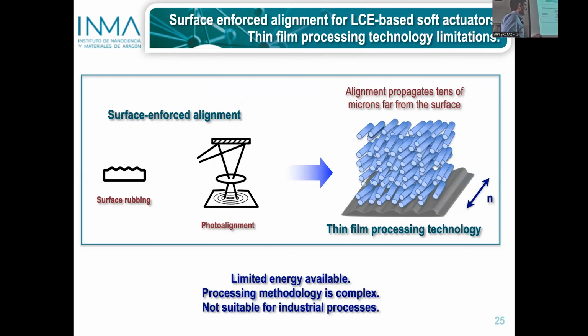Okay, I showed you until now a couple of techniques based on treatment of surfaces: the surface rubbing, the photo alignment. All of them accomplish the alignment of the liquid crystal by interaction with this surface. But I mentioned before that this alignment propagates only a few tens of microns. So the films we can generate with this technology are in the order of tens of microns, not more. So the amount of energy available in this actuator is rather limited. Also, the processing methodology is quite complex.